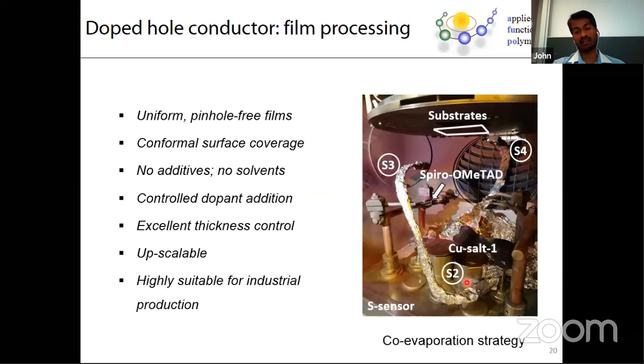Anyway, the benefit of moving from solution process to evaporation process was really helpful for us. It has its own intrinsic benefits, such as producing very uniform pinhole-free films, no matter how rough your surface could be. Through evaporation, you can conformally cover your surface, and no additives or solvent are needed. Very importantly, you can control the concentration of the dopant, in our case the copper salt, in a very accurate way by using a few sensors. We can also control the thickness, and this technology can be easily upscaled to different devices or applications, because evaporation is a basic method that people use in industry for preparation of screens and many other technologically relevant applications.